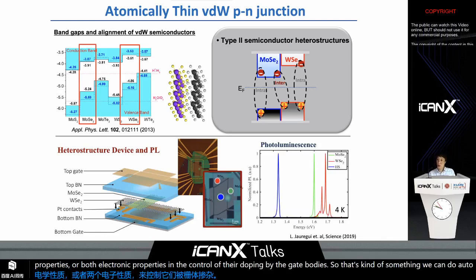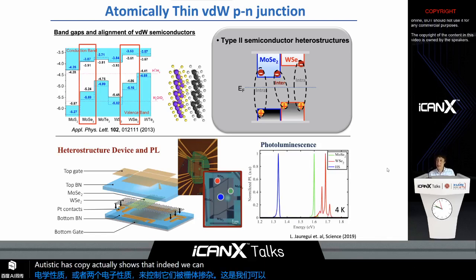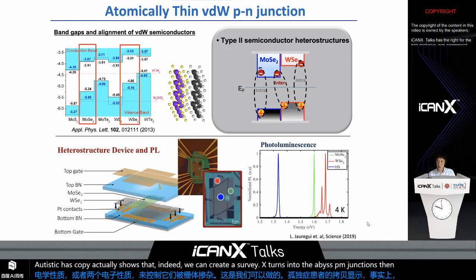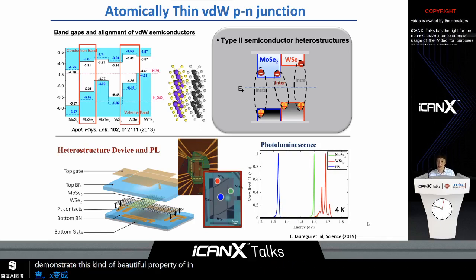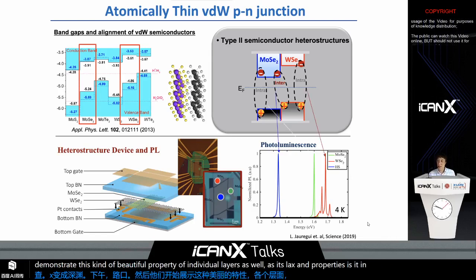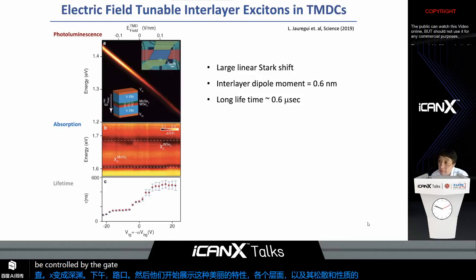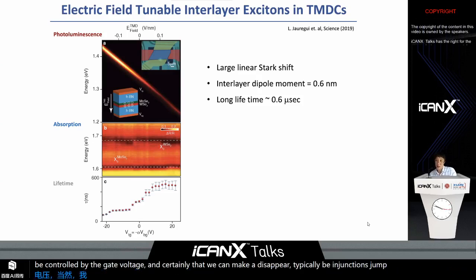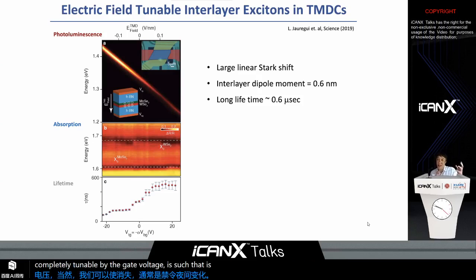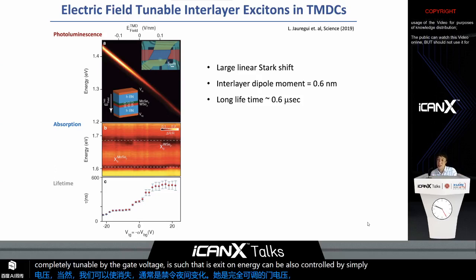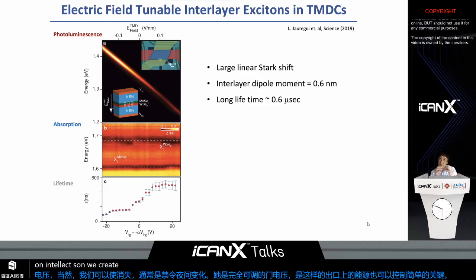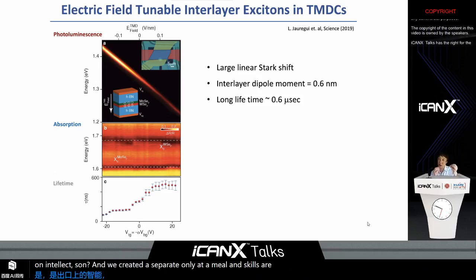Optical spectroscopy shows that indeed we can create excitons in these p-n junctions. Then they demonstrate beautiful properties of the individual layers as well as these interlayer exciton properties. These interlayer excitons, it turns out, can be controlled by the gate voltages. Certainly we can make atomically thin p-n junctions that, unlike the bulk p-n junction, are completely tunable by the gate voltages, such that the exciton energy can also be controlled simply by the gate voltages. And this interlayer exciton we create is separated on the atomic length scale, but is completely controllable by the gate voltages.